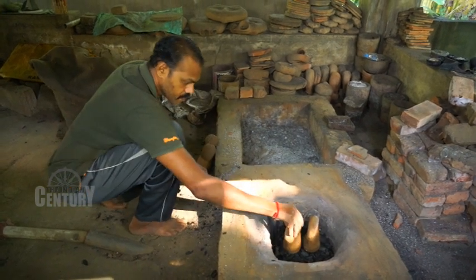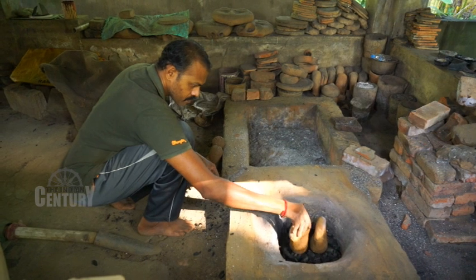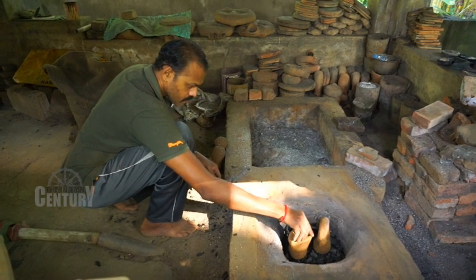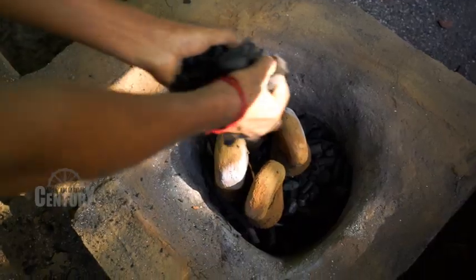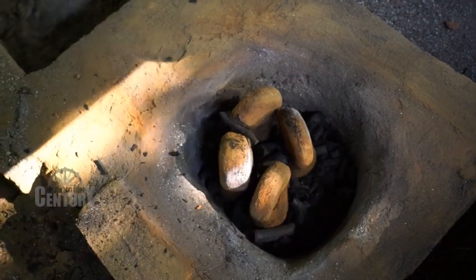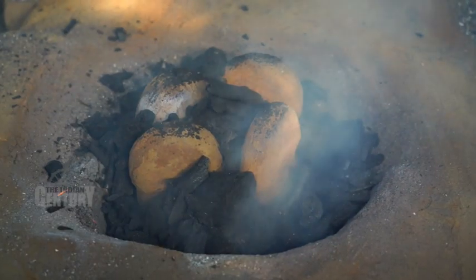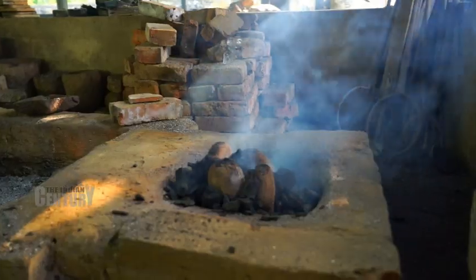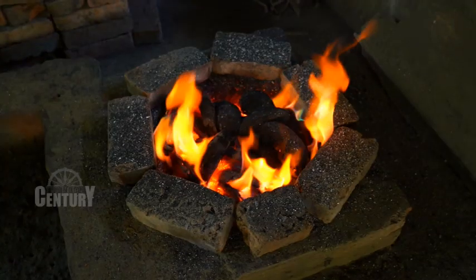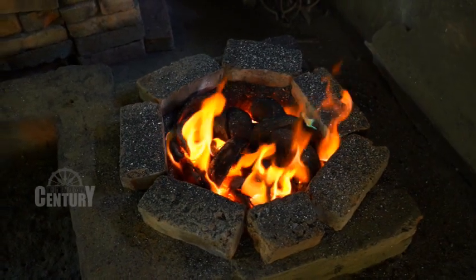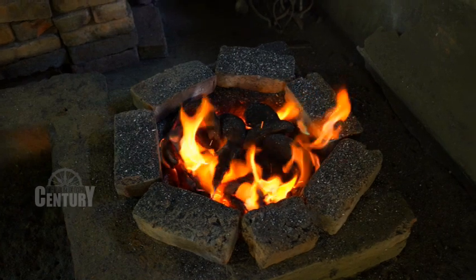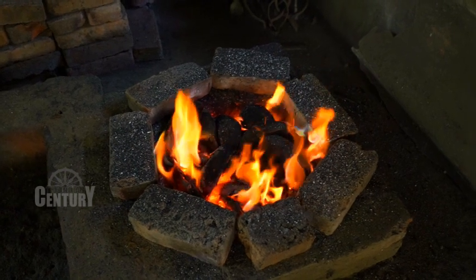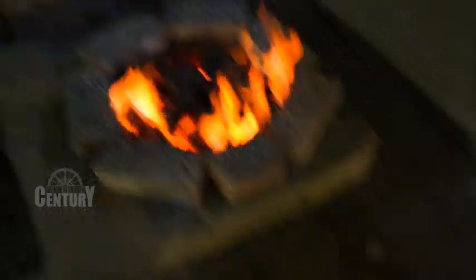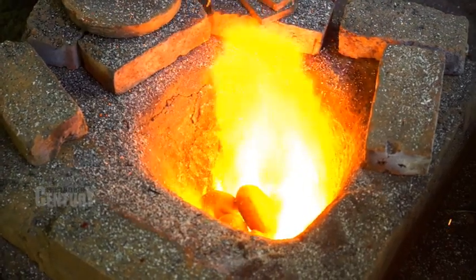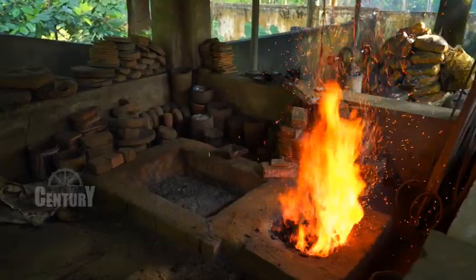The fire is ignited and it is heated to over 745 to 760 degrees Celsius. Once the required heat is obtained, the mold is picked up carefully by the lifting tongs and tilted upside down, so that the molten metal is poured into the mold from the opposite side of the air vent hole. The mold is kept in a place to cool down.